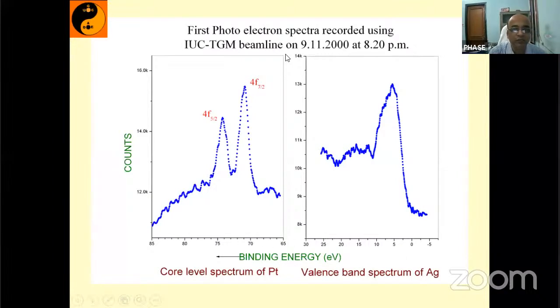These are the first spectra, generated with our old spectrometer. It is platinum. You can see the platinum core levels 4f 5/2 and 4f 7/2 this way. And this is a spectrum which was generated within 1 or 2 minutes.